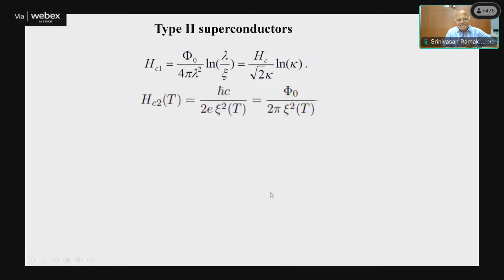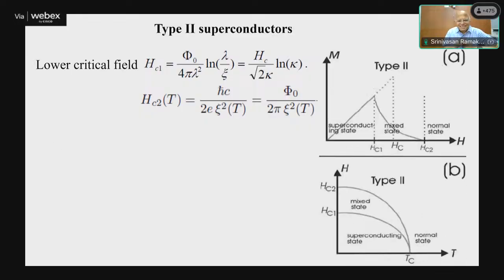So the final expressions for type 1 and type 2 superconductors are derived from Ginzburg-Landau equation 1 and equation 2. So this is the critical field below which you have a Meissner state, where phi naught is the flux quantum, lambda is the penetration depth, xi is the coherence length, Hc is the critical field, kappa is the lambda by xi Ginzburg-Landau coefficient, and ln kappa. So this is the critical field in a type 1 superconductor, where you see an expulsion of magnetic flux. It will behave like a Meissner-Ochsenfeld state.